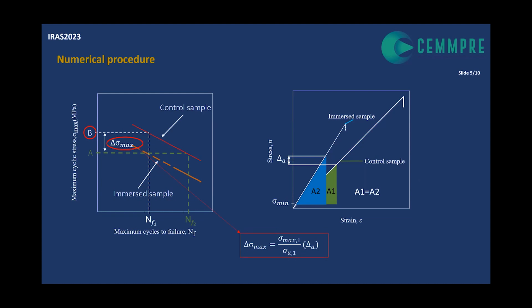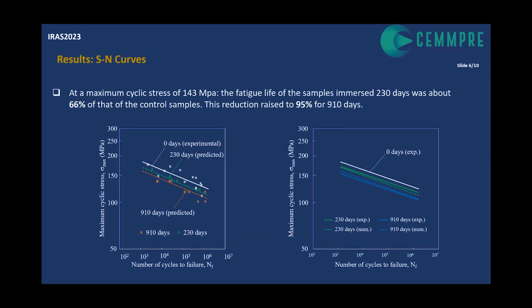Regarding the results, firstly, the experimental results show a significant reduction of the fatigue life. For instance, at the maximum cyclic stress of 143 megapascal, the fatigue life of samples immersed for 230 days was about 66% of that of the control samples. This reduction was raised to 95% for samples immersed for 910 days.